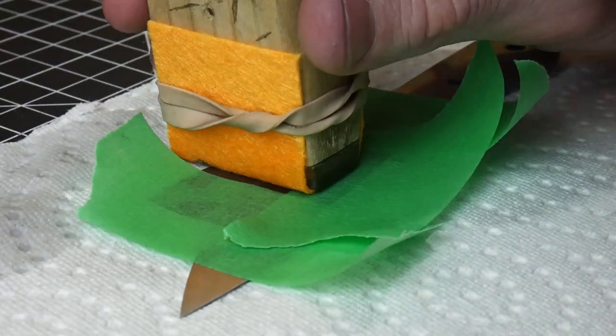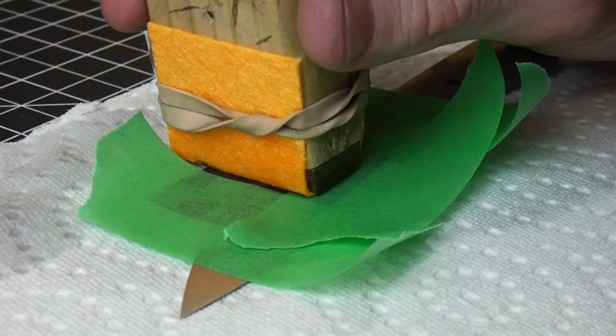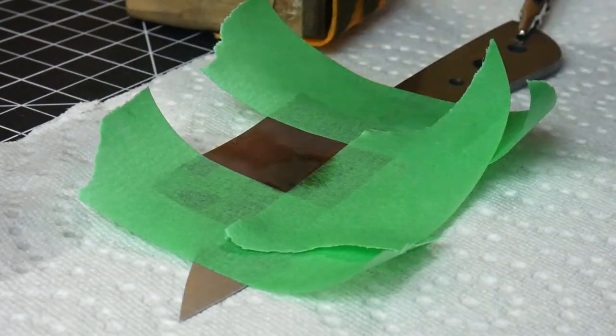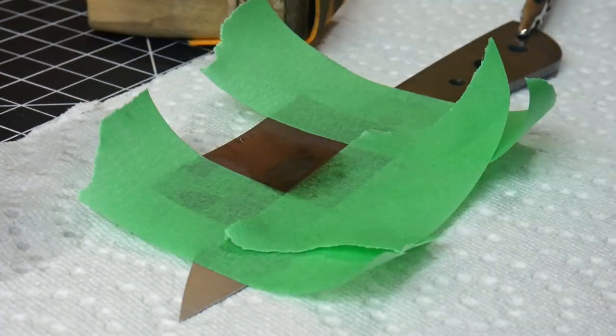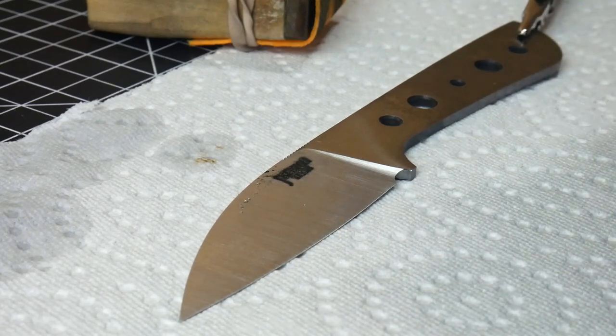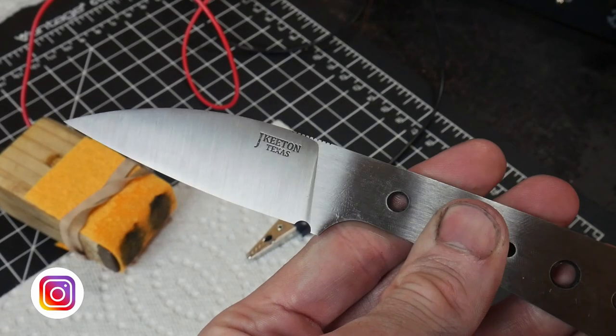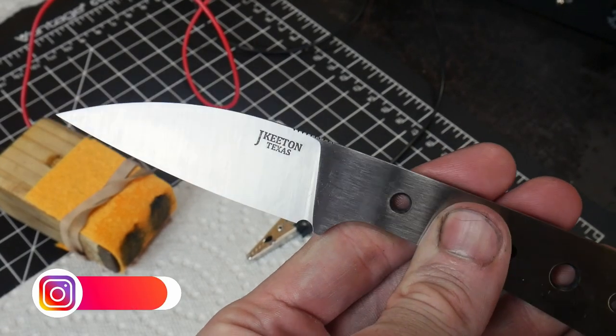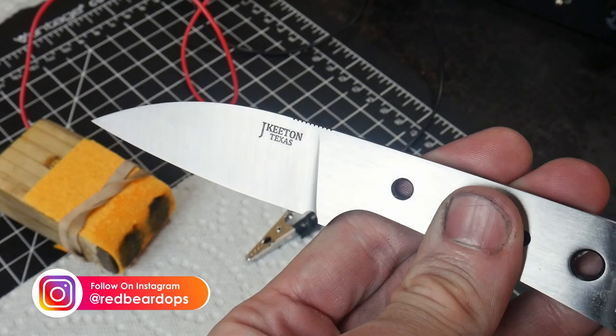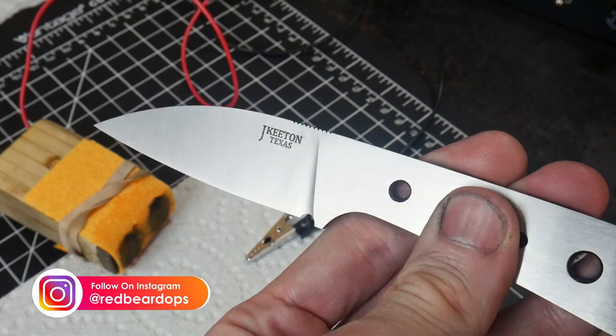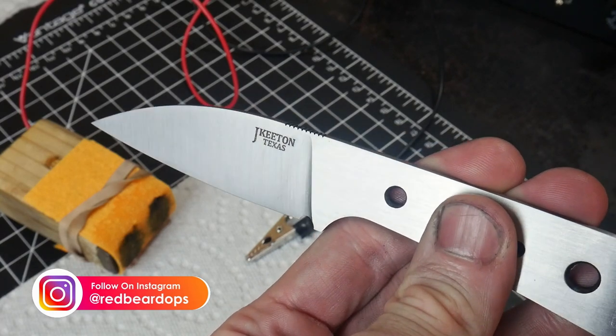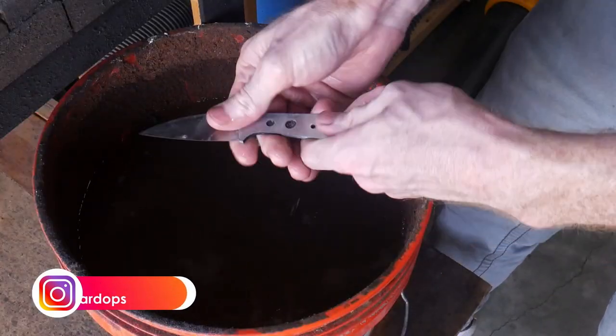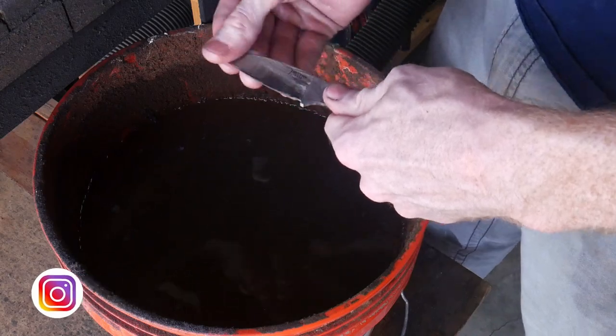The etching process for this blade was as follows. I hit it with 12 one-second cycles at DC, and then three one-second cycles at AC power to make sure it's nice and dark. Then I went back to the belt sander and did two or three more passes with the Scotch-Brite belt to clean it all up.